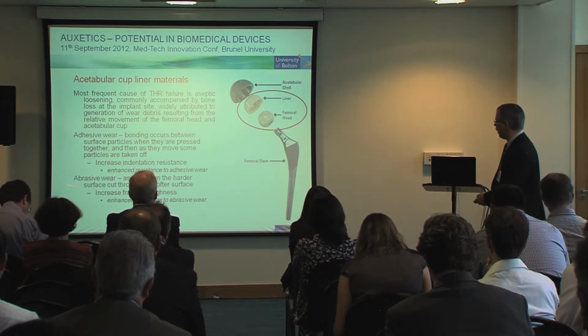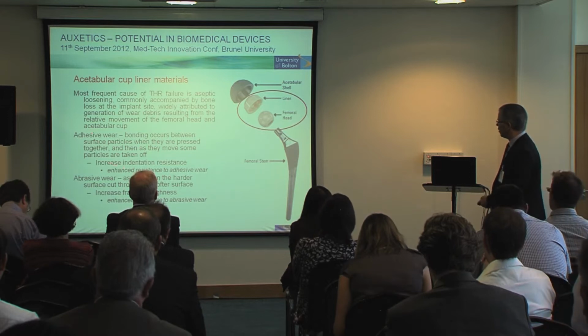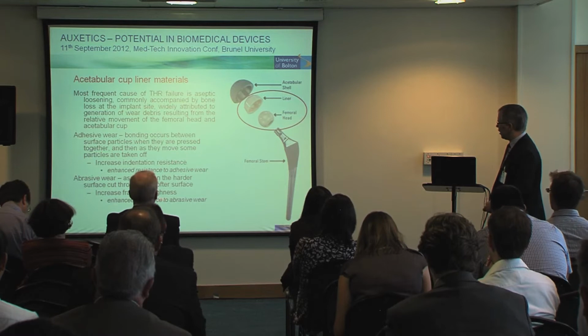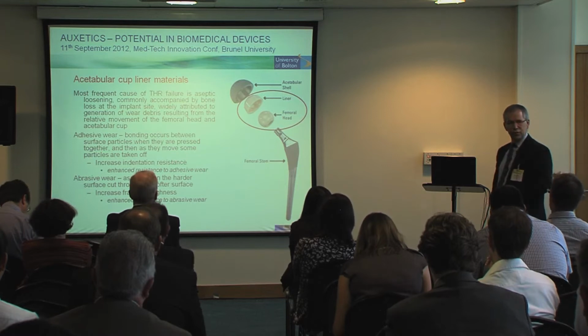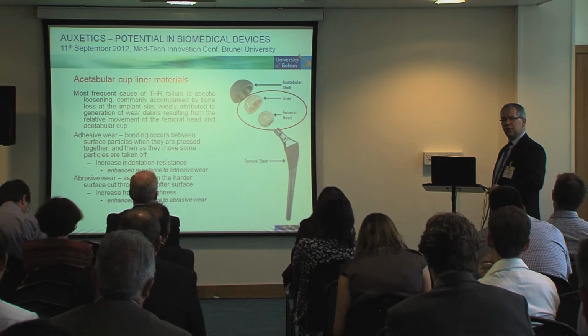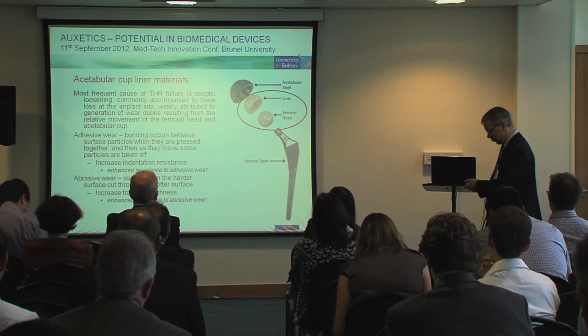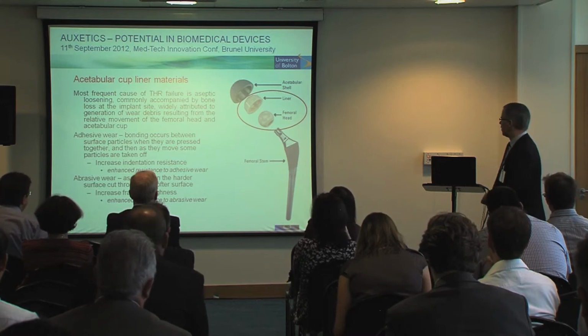And the main causes of wear in these materials are adhesive wear, which is related to indentation resistance, and abrasive wear, which is related to fracture toughness. So if we can increase those two properties, we should be able to increase the wear properties of these materials.